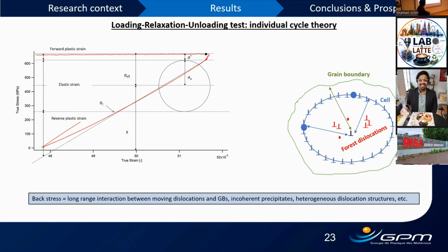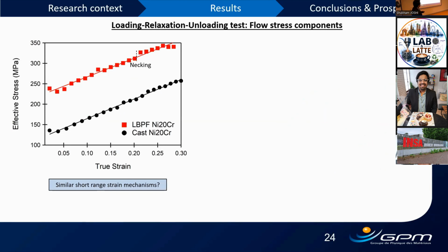Another aspect of this flow stress partition is back stress. Again, this lonely mobile dislocation, if it has long-range interactions with grain boundaries, heterogeneous dislocation structures, dendritic structures, or incoherent precipitates, this interaction constitutes back stress. So here we can understand and go deeper into the origin of flow stress partitions. Mechanically, using the same unloading sequence, we can use the position of the elastic domain to quantify the back stress. Having done this analysis, let us look at the effective stress versus true strain graph.